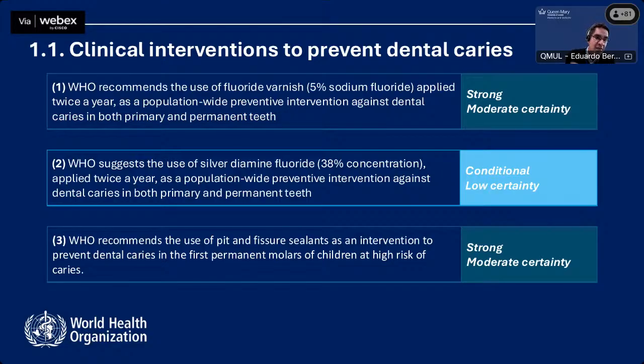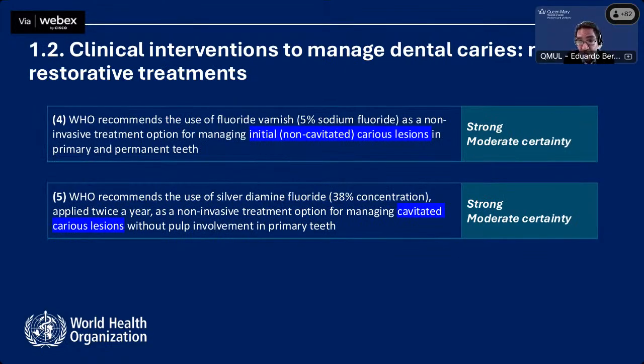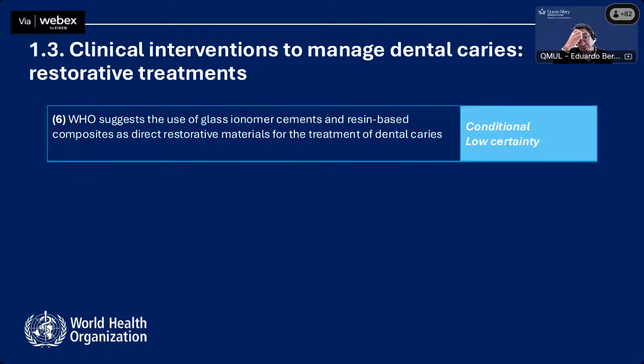In terms of prevention, the three products had some effect, especially fluoride varnish on the top and then fissure sealants at the bottom. For silver diamine fluoride, the recommendation was only conditional. Now, moving into non-restorative treatments, the two recommendations were strong. What I would like to highlight here is the text in blue. Fluoride varnish is recommended for managing initial caries lesions, non-cavitated lesions, while silver diamine fluoride is for arresting cavitated caries lesions. Moving into restorative treatments, there was sufficient evidence to make a recommendation regarding the use of glass ionomer cements and resin-based composites, although the evidence is of low certainty and the recommendation is conditional.